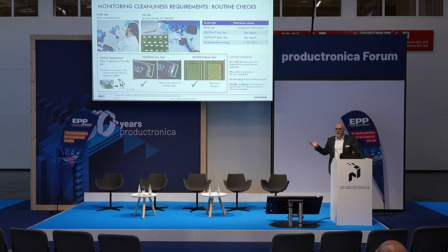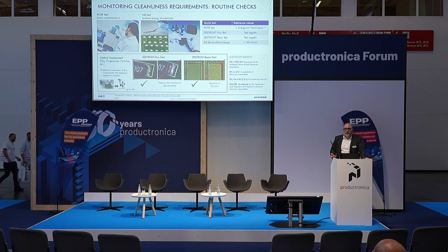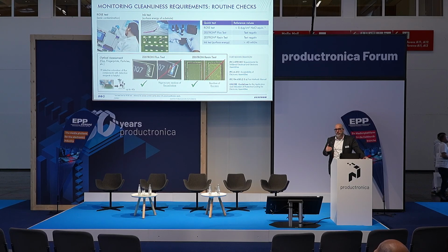So there are some routine checks, as I just mentioned, the so-called ROSE test for ionic contamination. This is a test where you put the PCBA under a test liquid, basically a water mixture. And then the ions are washed out, and basically you measure the conductivity of the remains, and then you get a good picture of how big your ionic contamination is. So for normal process monitoring, this is good enough because you can check, depending on the limit that you set before, if your process is still stable. And same with ink tests for surface energy. These are the very easy tests, and flux and resin tests.